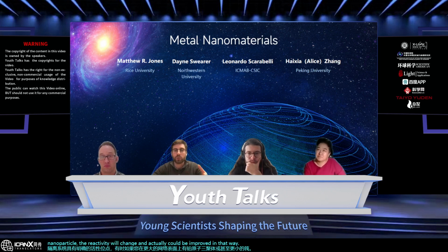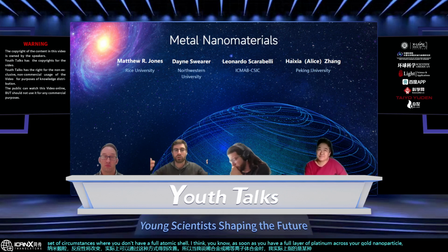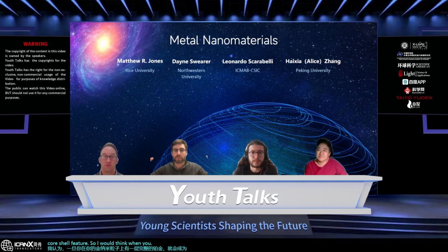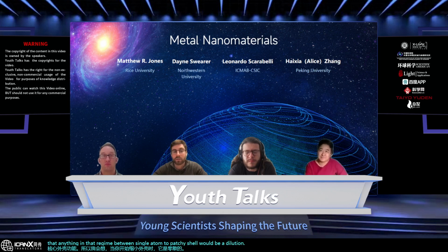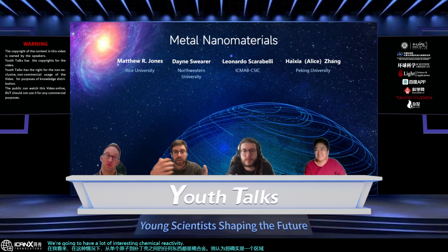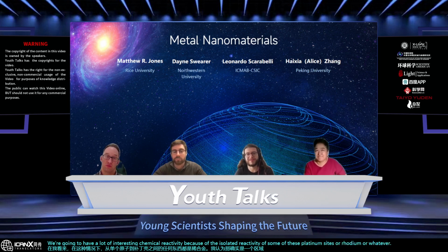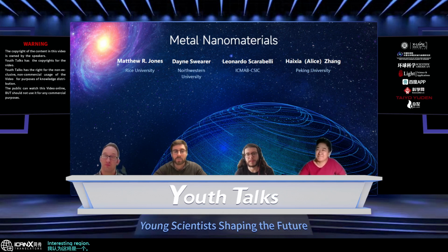And so when I say a dilute alloy or a dilute plasmonic alloy, I'm really referencing a certain set of circumstances where you don't have a full atomic shell. I think, as soon as you have a full layer of platinum across your gold nanoparticle, in my opinion, that becomes a core shell feature. So when you begin to shrink that shell down so it's patchy, anything in that regime between single atom to patchy shell would be a dilute alloy, in my opinion. I think that's really a region where we're going to have a lot of interesting chemical reactivity because of the isolated reactivity of some of these platinum sites or rhodium or whatever your favorite transition metal is. And I think that's going to be an interesting region to explore in coming years.